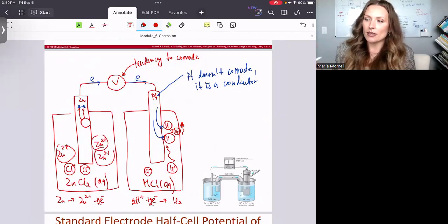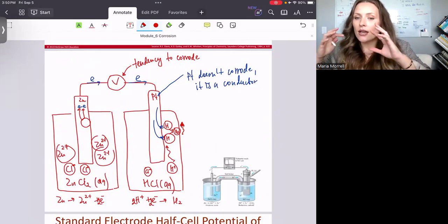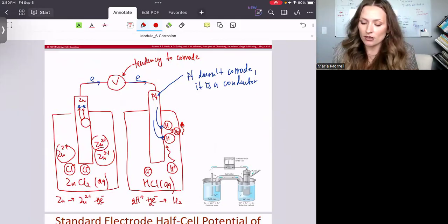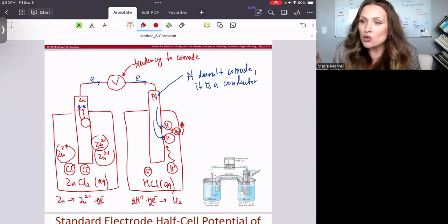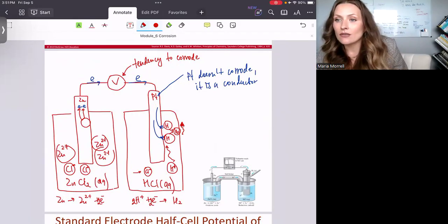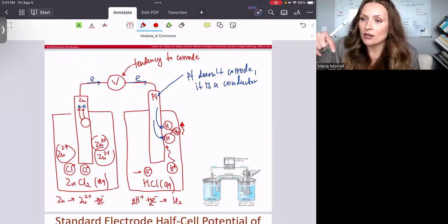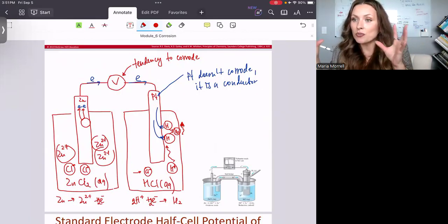And you know that these are positively charged, so you're bringing more and more of this positively charged zinc, and in a sense, you're building positive charge in one solvent, right? And on the other hand side, you are consuming your positively charged hydrogen ions, and that means now you have depleted the hydrogen ions, and you have more and more of the negatively charged chlorine ions, in a sense that now I have this charge buildup.